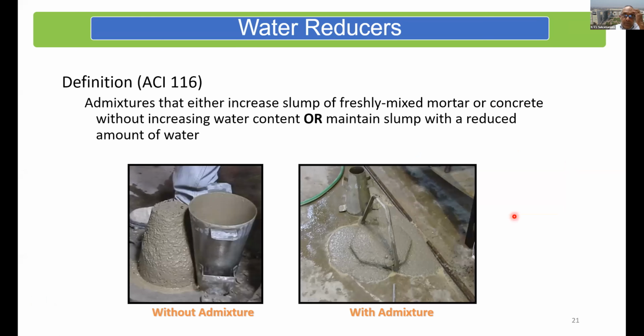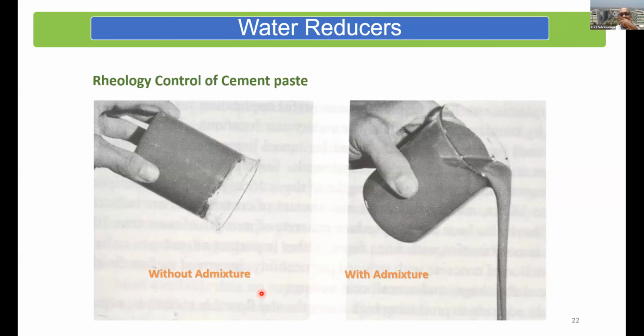One of the most commonly used admixtures everybody is familiar with is the water reducer. It basically reduces the demand for water. So here you have concrete that has a slump. If I add a little bit of high range water reducer to it, it basically starts flowing. And this is just to show you what this water reducer does. This is one of the additives we add to concrete. And basically it decreases this property called yield stress. Yield stress is a measure that we get from rheology,